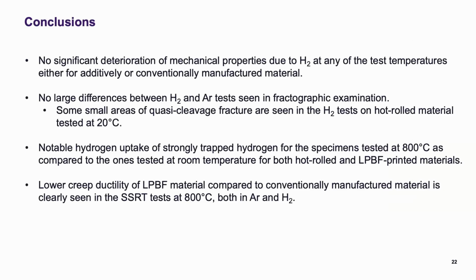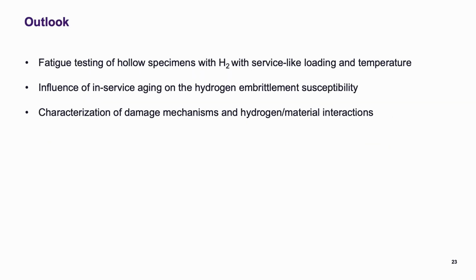The conclusions are that we don't see any significant deterioration of mechanical properties due to hydrogen at any of the test temperatures for any of the materials. We have small localized areas of quasi-cleavage, but it's not really reflected in the test results. The lower creep ductility has nothing to do with the hydrogen, it's expected. And of course, at 800 degrees we do have hydrogen uptake during the testing. The outlook is that we need to develop the testing methods. We want to do fatigue testing of hollow specimens with service-like loading and temperature, so basically thermomechanical fatigue testing.